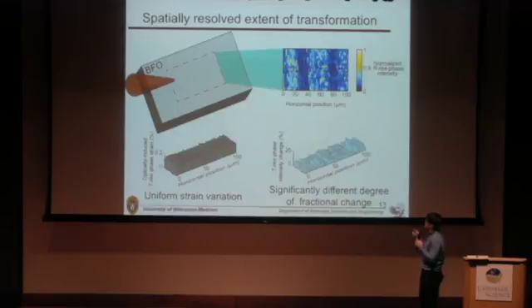And we measured the strain and intensity changes within the region indicated by the red dotted boxes, and see the strain variation is quite uniform, but the intensity changes of the T-like phase significantly varied depending on the position of the sample. We can learn two things from this result. One is the structural phase transition is not solely explained with the strain, and also there should be another factor contributing to the phase transition. And another thing we can learn is the strain variation was uniform. So strain, optically induced strain, is only a function of the number of charge carriers.